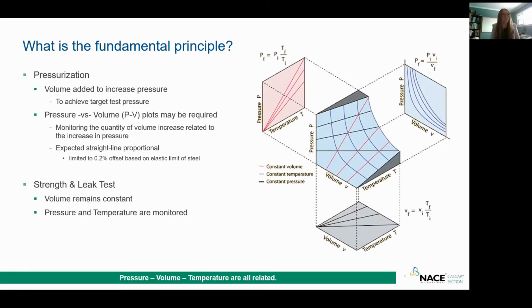If you've learned one thing from my presentation today, or you recall from your previous education, it is the fundamental principle that pressure, temperature, and volume are all correlated. I pause because pressure, temperature, and volume are all correlated. So when we go back to thinking about our different test stages, when we're doing our squeeze, we're adding volume into the pipe to increase pressure. And so when we go up to greater than 100% of specified minimum yield strength, you're required by CSA to do something called a pressure volume plot, okay?